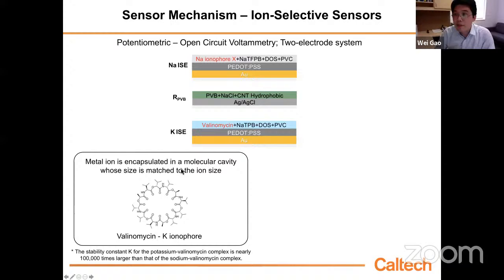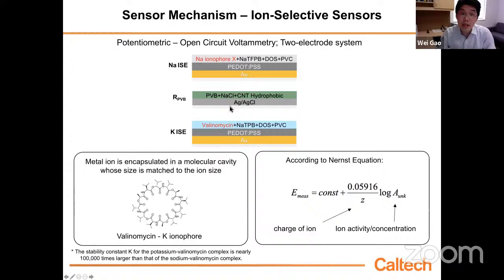Look at the potassium ionophore valinomycin. This molecule has a ring structure. The ring size actually is matched to the potassium ion. So when the electrode is put into a solution containing potassium, this ion will enter this ring and set the voltage of this working electrode. According to the Nernst equation, the measured voltage difference between the two electrodes can be expressed like this. The voltage difference has a log linear relationship with the ion concentration. The slope is 59.16 millivolts per decade of concentration. This is for sodium and potassium because z, the charge of the ion, equals one, right?